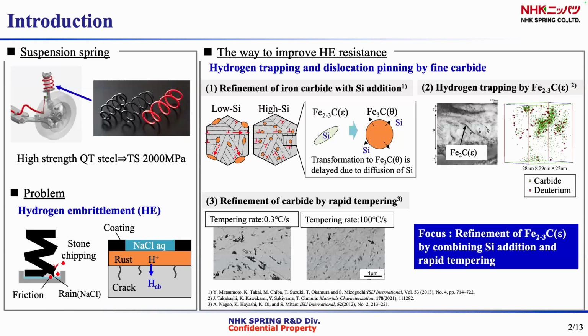Recently, it has been reported that the epsilon carbide may have hydrogen trapping ability. Additionally, the carbides have been refined by rapid tempering. Therefore, we focus on the precipitation of epsilon carbide by combining silicon addition and rapid tempering.